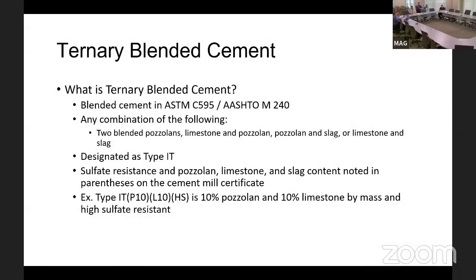A ternary blend is also a C595. It's any combination of the following. You could have two blended pozzolans. Pozzolans could be a natural pozzolan and a fly ash, or you have limestone and pozzolan, pozzolan and slag, limestone and slag. It's designated as Type IT. Sulfate resistance and pozzolan, limestone, slag content noted in parentheses are also reported in a mill cert. So an example here is a 1T P10 L10 HS. It's basically a 1T cement with 10% interground pozzolan, 10% limestone, and it's high sulfate resistant.